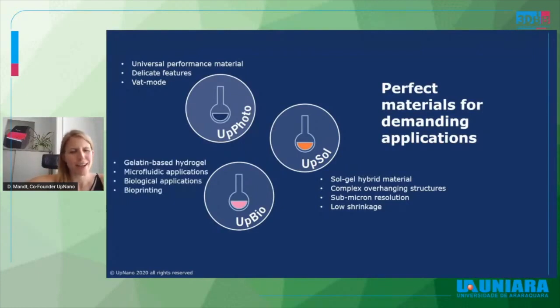And last but not least, our biomaterial, the biocompatible material, which is especially suitable for bioprinting and biofabrication approaches. This material is a gelatin-based hydrogel material with a high water content, about 80%. This material comes as a kit, so it can be mixed together with a cell culture medium, for example, but when you do real bioprinting, it can also be mixed together with the cell solution, so that the cells are really distributed in the material. And it is especially intended to be used for biological applications and real bioprinting.